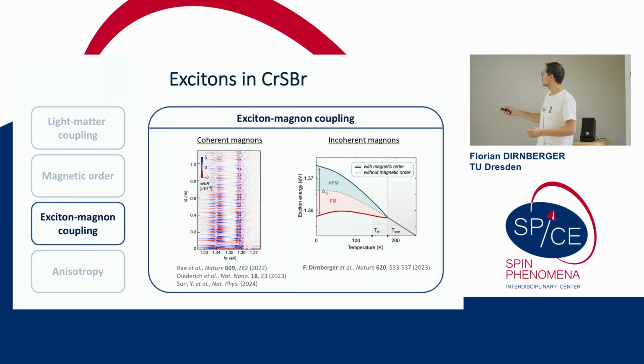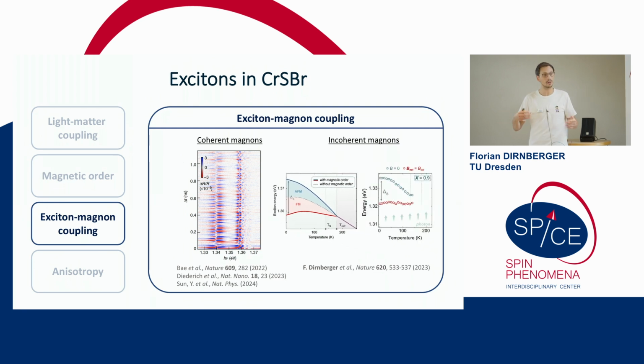It turns out when we actually look at an exciton-like polariton branch, for example, as a function of magnetic field and temperature, this is in reasonable agreement with what we see in the experiment. So the excitons in chromium sulfide bromide couple to the coherent magnons, but they also couple to these incoherent fluctuations of the magnetic order. I think this is also really relevant to understand the physics of the excitons.